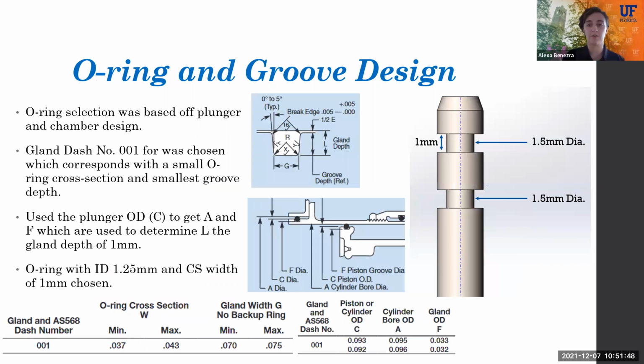So the O-ring and groove dimensions were designed with guidance from the Parker O-ring handbook. There isn't an exact principled method for selecting an O-ring and designing the groove because you usually need an O-ring to design the groove and you need a groove to choose an O-ring. So it takes some trial and error with both of them. Since we know the plunger and chamber sizes that were determined based on the volume requirements for the pipette, we used the handbook to help to determine the groove depth and gland width.